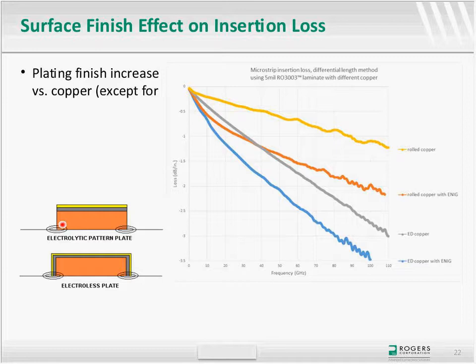So your current running through here is not affected. But as I said, typically this is something we find more for the defense markets, because they're going to be doing some wire bonding. So they have to have what they call hard gold on the surface, and this is the way they do it. But it's a much more costly process. For circuits, this is the traditional way, and it will have that impact. We have separate presentations that they can reach out for if they need more detail on the subject that Rogers has presented, but that is something to consider. So here's the start where you will see the data on ENIG, which is electroless nickel immersion gold.